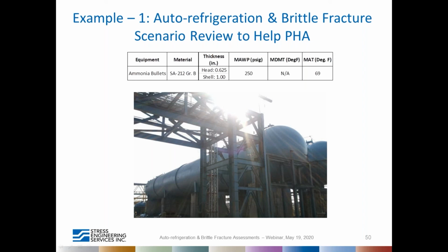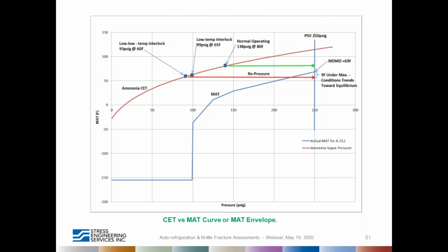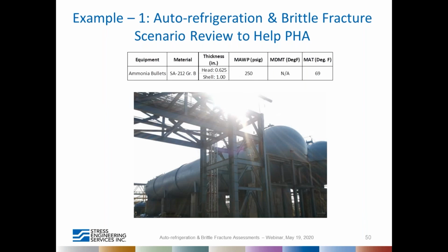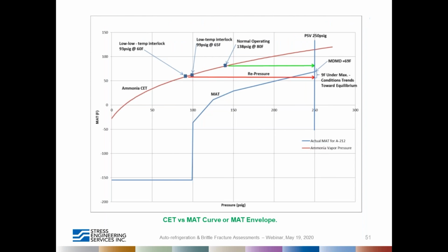So the material of construction is given here. This is a very old ammonia bullet, and the thicknesses are of concern. As you can see, the thickness is greater than ½ inch for both shell and head. And the MAT, if it were to be determined from the exemption curves, is 69. So you would have to develop the MAT curve for this one, and then look at the flash curve for the ammonia and look at the risks from that standpoint.